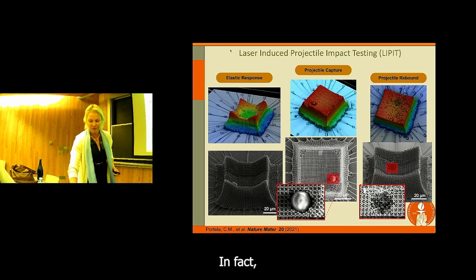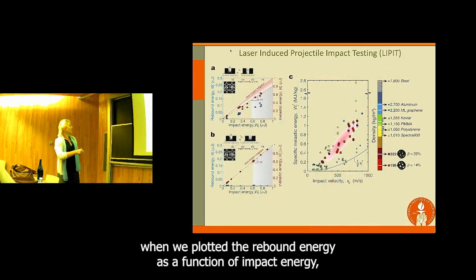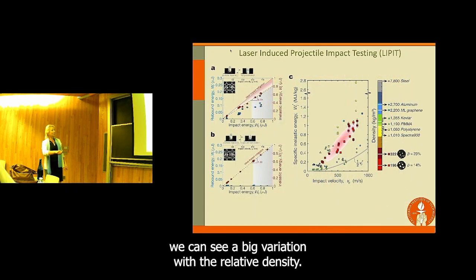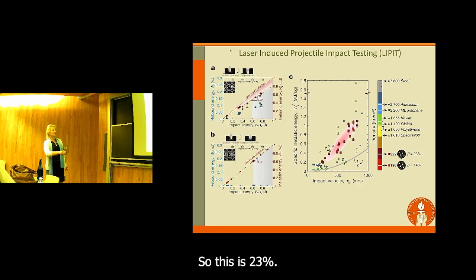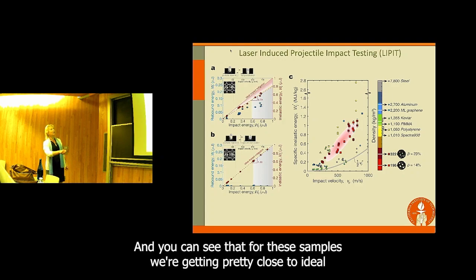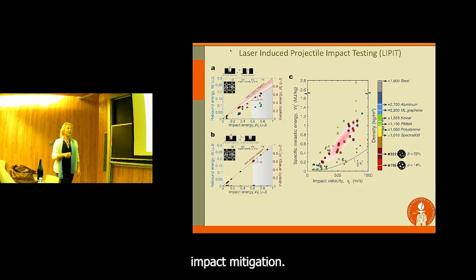And in fact, when we plotted the rebound energy as a function of impact energy, we can see a big variation with the relative density. So this is 23%, this is 14%. And you can see that for these samples, we're getting pretty close to ideal impact mitigation.